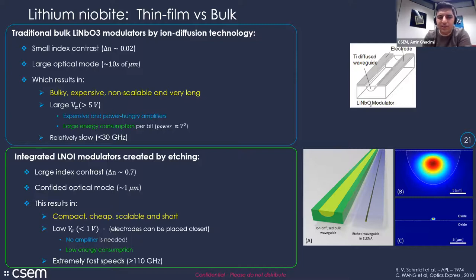So really, all I'm saying is that you might take this lightly, but the core innovation of LNOI compared to traditional lithium niobate comes only from this mode size reduction. And that's a significant reduction. It's in the order of 100x reduction of mode volume. And this is how you really gain on these things.